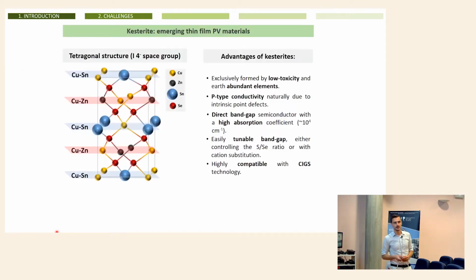So, given the importance of kesterite, what are the characteristics of this material that make kesterite very interesting for photovoltaic application? First, if you take a look at the structure, this is a tetragonal structure. It's very related to the copper indium gallium diselenide structure, and is very related to the cadmium telluride structure, and at the end, very related to the silicon structure. Basically, if in the silicon structure you take two atoms, one silicon replaced by cadmium and the other by tellurium, you form the zinc blende structure that is the cadmium telluride structure.